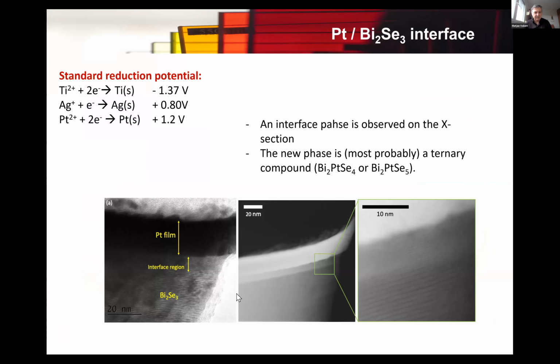What is the next one? Platinum. You see, it's even more noble than silver. So here we went straight in. Of course, we deposited platinum on the surface of bismuth selenide and went straight into the transmission electron microscope and inspected the cross section of this film. And what we have seen is, again, an interaction. So this white part here is platinum, and this part here is bismuth selenide.